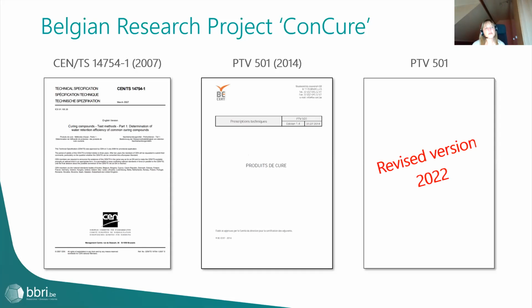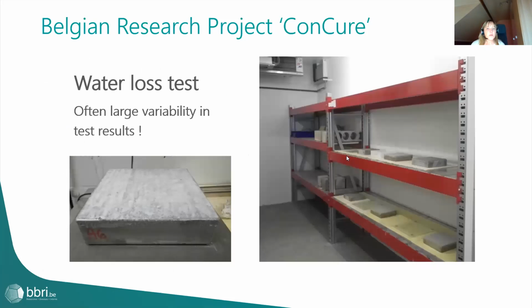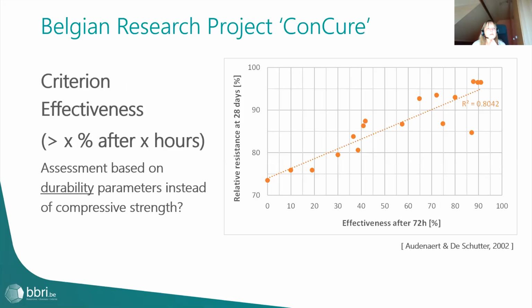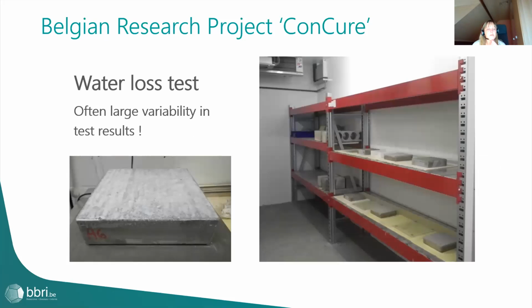And this document does not yet give full satisfaction. And as a result of our research work, we hope to be able to publish a revised version within 2 years. The principle of the lab test is simple at first sight. It's a matter of comparing the loss of mass of specimens covered with curing compounds with that of reference specimens. But there are many parameters involved, including the concrete mix design, the way of removing bleeding water, and so on. So the method often exhibits large variability in test results, and this makes it difficult to decide whether the curing compound passes or fails the test.